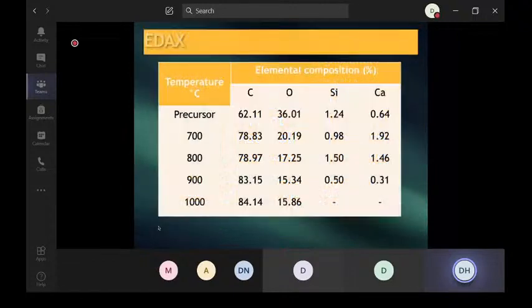So when we did the EDAX of that, you can see the EDAX gives the elemental composition of such kinds of nanoparticles. You can see the precursor, before making the nanoparticle, where carbon is 62%, oxygen is 36%, silicon is 1.2%, and calcium is 0.64%. And when we pyrolyzed it, that is, made the nanoparticle at higher temperatures like 700, 800, 900, 1000, you can see the carbon percentage increases with respect to temperature. At 1000 degrees, you get only carbon and oxygen. All other elements will go away. So you have 84% carbon, which is pretty good from an application point of view.